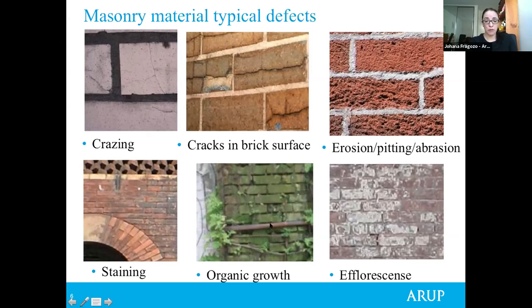The organic growth, signs to look for: algae, mold growth, and it's usually due to water and moisture presence on the surface of the brick, or even behind the brick wall itself. And efflorescence usually manifests as a white powdery substance on the surface of the brick. Most of the probable causes are water flowing through the masonry that induces the migration of water, and that in combination with soluble salts present in the brick, the mortar and the grout cause this white substance. And then again, it's mostly of aesthetic nature.